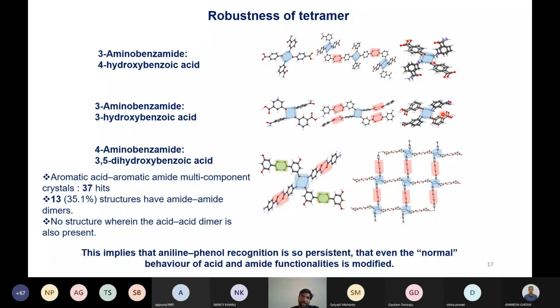We also tried to check the robustness of these tetramers. So what we did, we tried co-crystallization with 3-aminobenzamide and 4-hydroxybenzoic acid, and 3-aminobenzamide and 3-hydroxybenzoic acid. The purpose was just to see whether, under the influence of the stronger acid-amide synthons, this aminophenol recognition breaks, but it didn't break. Instead, we observed in some cases that the amide-amide dimer forms, even though there is a possibility of formation of acid-amide, and that means this tetramer is driving the primary synthon of these co-crystals.